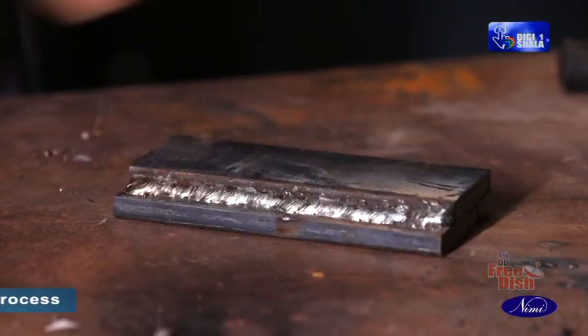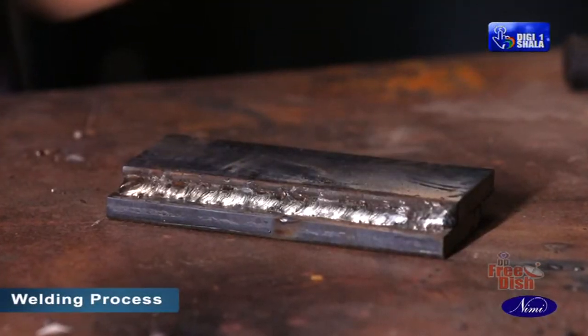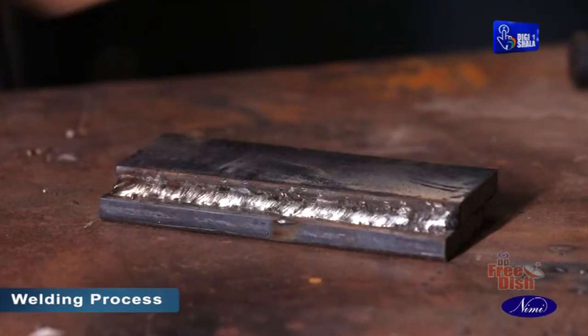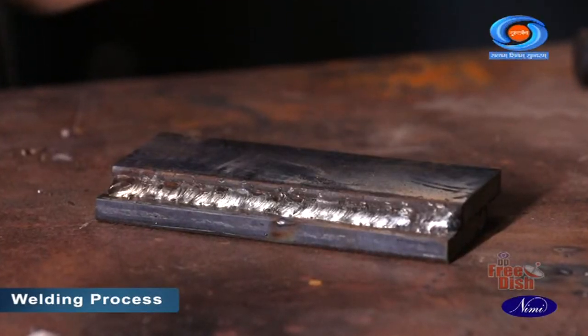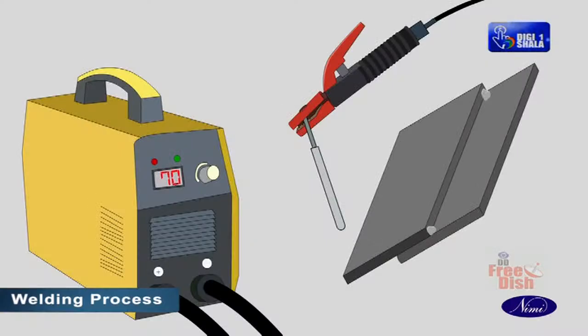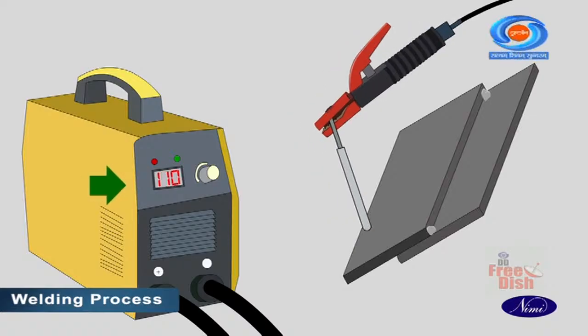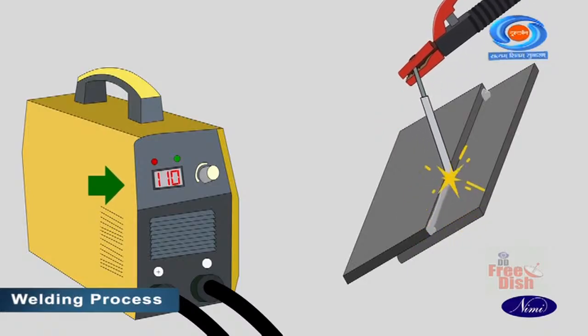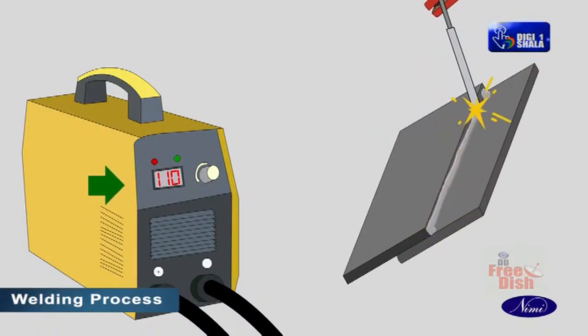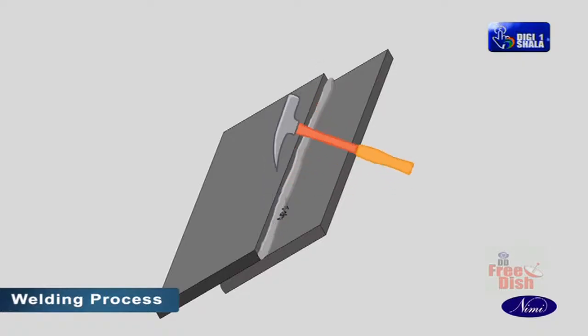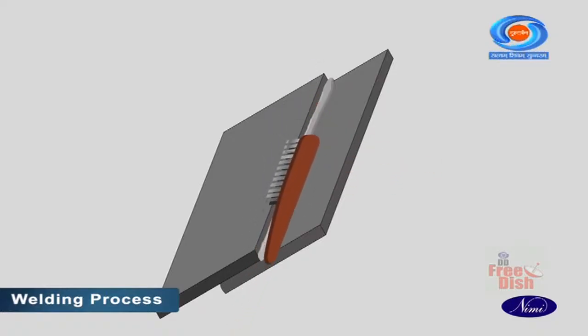Now let us look at how to perform a fillet lap weld on an MS plate in a flat position by the SMAW process. Deposit the root run using a 2.5 mm dia medium coated MS electrode with 100 to 110 amps current. Deslag and clean the root slag thoroughly.